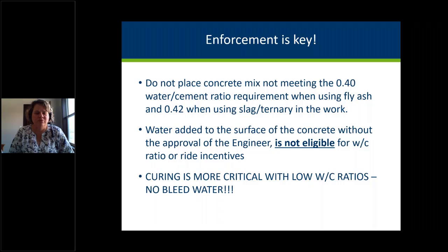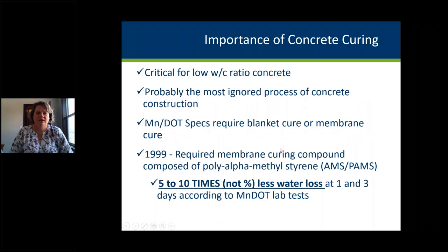The other biggest thing we learned when we pulled the water out of the mix was that curing was more critical. We didn't see bleed water anymore with these mix designs, so we had to look at changing things. And with that, curing became extremely important to us. It was always important, but it became much more critical. What we found was it was probably the most ignored process of concrete construction, even though it was one of the most important. Our specs currently do allow the contractor to use a blanket cure or a membrane curing compound. We do see the contractors, unless there's cold weather, using membrane curing compound as their primary method.